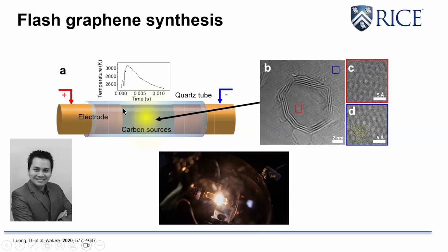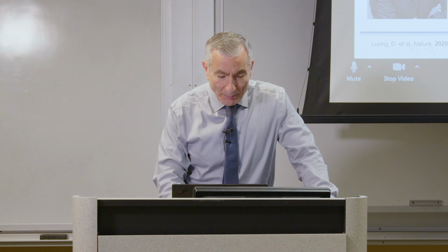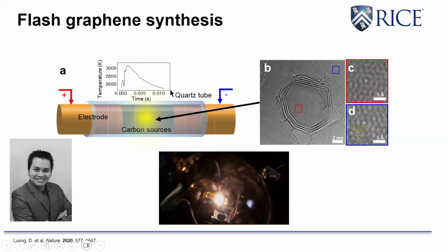Now, if you look at this, this is a time in seconds. So this is 3 milliseconds. At 3 milliseconds, it's heated to over 3,000 Kelvin. 3,000 Kelvin is almost the same as 3,000 centigrade. They're only 273 degrees different. So when this is like 3,200 Kelvin, it's about 3,000 centigrade. That's screaming hot in 3 milliseconds. And then it cools very rapidly too. And you see a big burst of light when that happens.